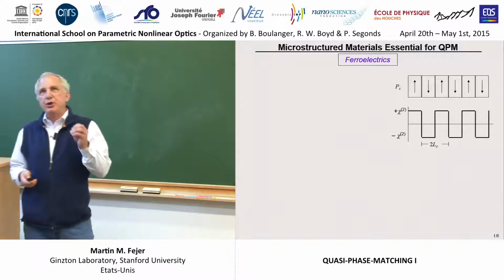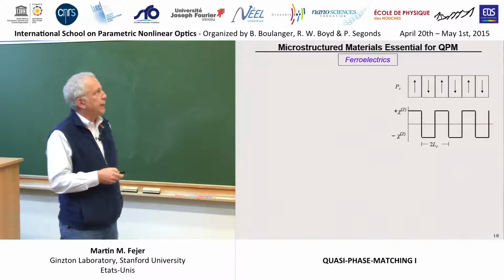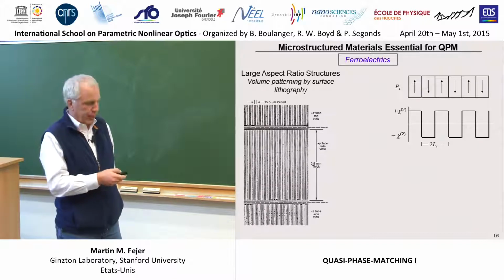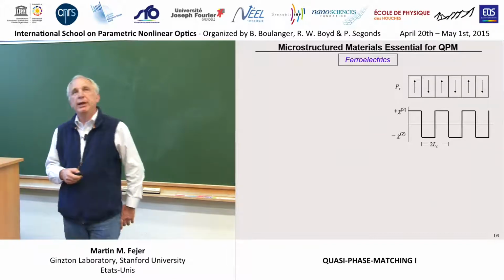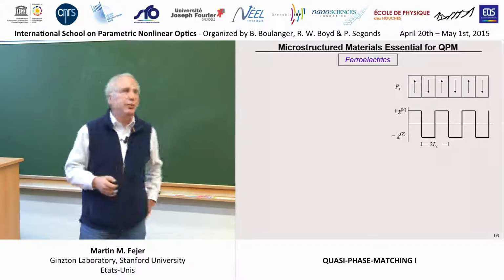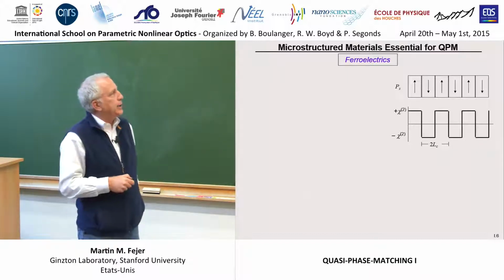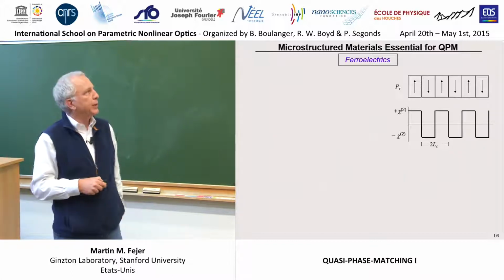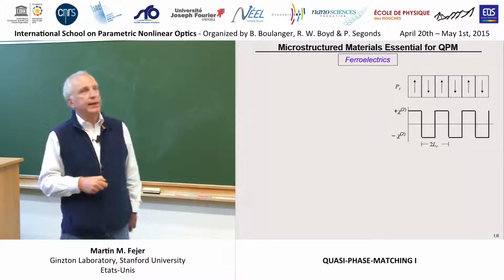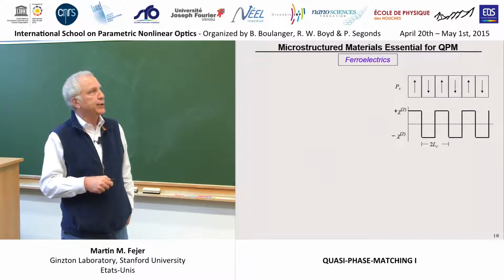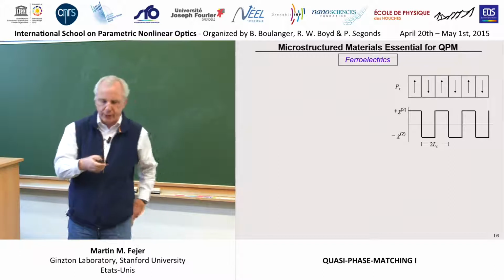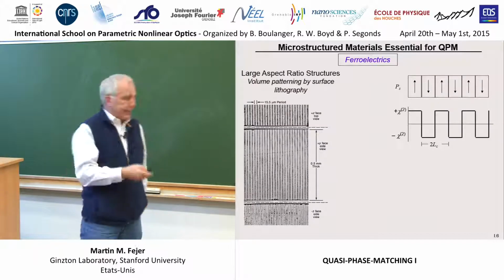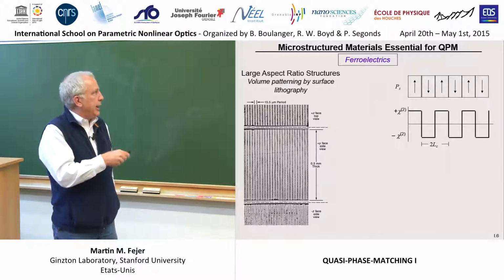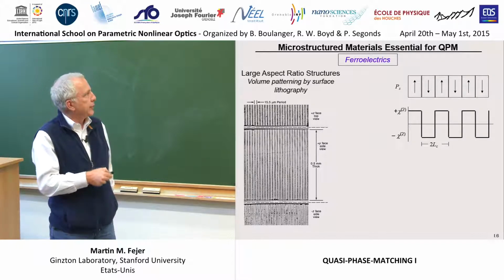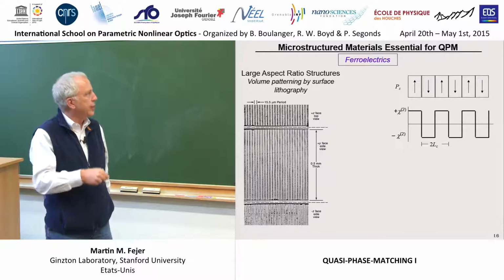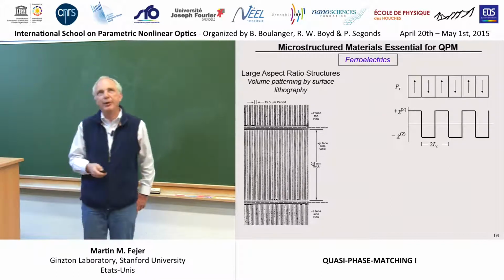By far the best developed such material system are the ferroelectrics. These are materials with domains of spontaneous electric polarization, akin to the spontaneous magnetic dipole moments that appear in ferromagnets. And in the simplest 180-degree ferroelectric, the relationship of an up and a down domain is such that it will change the sign of the nonlinear susceptibility, just like slicing and rotating the crystal would. Techniques have now been developed where fine pitch patterns of the order of microns can be put through millimeters, or in some extreme cases even centimeter thick plates.